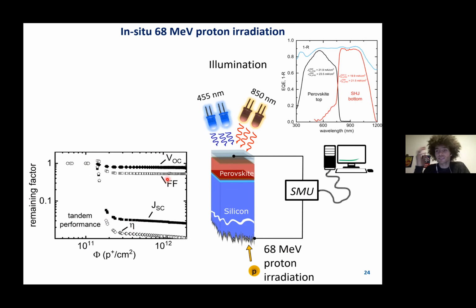Now this is a monolithic interconnection of the perovskite and the silicon. So we don't really know what is damaging here. Is it the perovskite? Is it the silicon? In order to find out, I did the following. I used these LEDs here and I reduced the intensity of my infrared LED while keeping the blue LED at a very high level. So in this configuration, the silicon subcell will limit the overall current because we are in a monolithic interconnection. Saying that, in this configuration, I will be sensitive to damage in the silicon subcell.